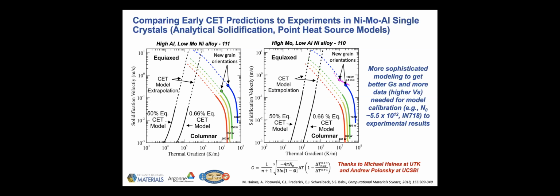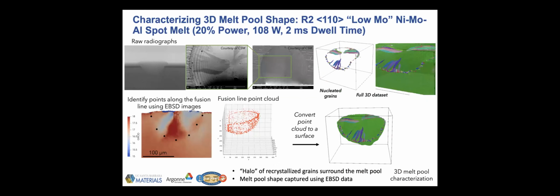And we took a step back from this to start thinking about how we could do better modeling, especially to get those better velocities and those better thermal gradients so we can start doing more informed modeling. In addition, one thing that we wanted to better understand was the ground truth of the melt pool shapes as compared to what we get in 2D with our synchrotron radiography compared to the actual 3D melt pool shape. This is work we're doing in collaboration with Teresa Pollock's group at UCSB, where we're using tri-beam to actually look at the 3D melt pools that we looked at with synchrotron X-rays at the APS.